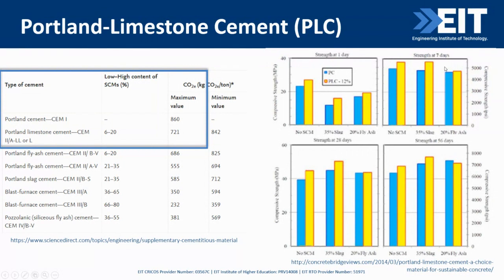So this is 1 day, 7 day, 28 day, and 56 days. The light blue columns are for a control mix using Portland cement, and the yellow columns are for another mix using Portland limestone cement. So we can see that the early age and the later age concrete strengths are similar when made with either Portland cement or Portland limestone cement, right? So this is very impressive.